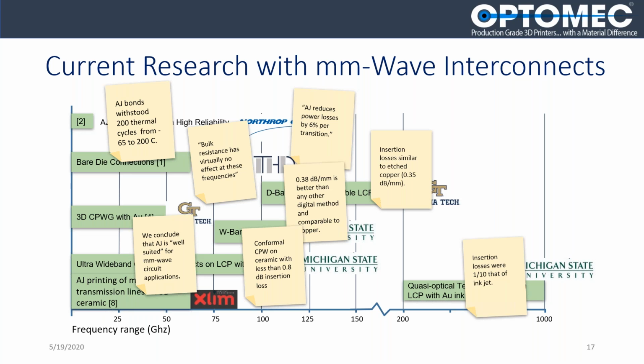And then when directly compared to inkjet, which is another printing technology that really only works on flat planar surfaces, the loss characteristics as we tested this on quasi-optical terahertz devices were 1/10 that of inkjet interconnects. So I put all this up here just to showcase the fact that we've worked with a lot of different customers on these printed interconnects for millimeter wave applications, and they all say the same thing: that they do perform very well, and they are reliable, and that we have quite a robust material set that we can offer to customers who are interested in doing this work.